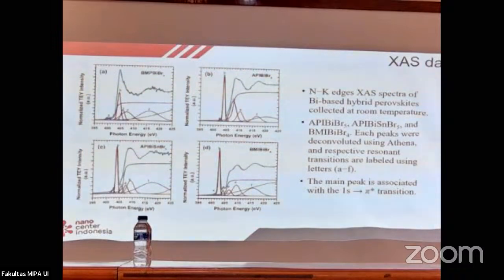So what is the key message from here? The consequence is that once having a very sharp transition, the probability of the electron jumping to the higher regime here will be compensated. And then when we do the Gaussian fitting, this complicated number of peaks tells you that once you jump from BMP to API system, you're basically tuning the initial main transition line. And when we change to another system by introducing tin instead of bismuth, we basically change one of the signatures here in a small range over here. But for detail, I will suggest please read our paper.